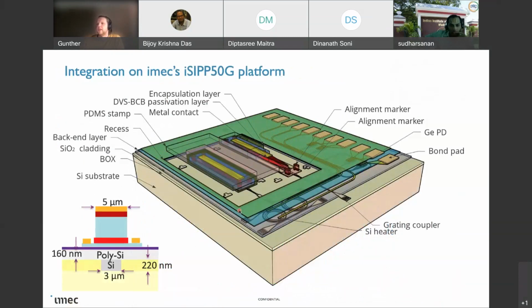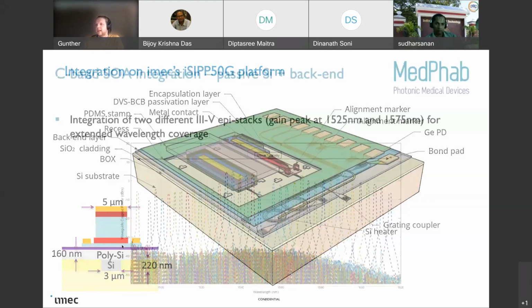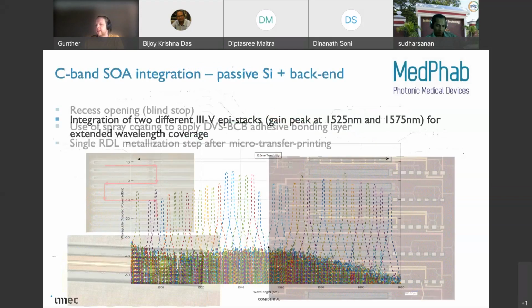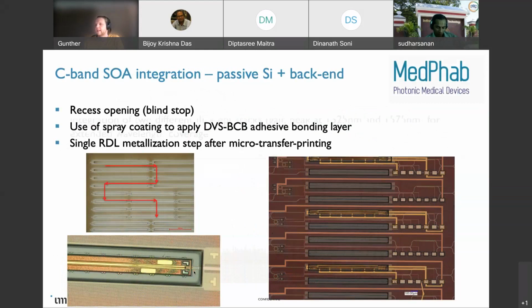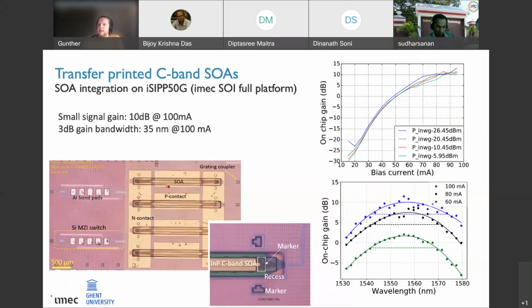Now, the next step then was to integrate on IMEC's iSIPP50G platform. I've already shown you this cross-section here. This is how the amplifier cross-section looks like. So it's similar as before. The mode is partially in the silicon and partially in the III-V. And I've also shown you here how we can transfer print inside recesses on the silicon photonics backend. So this then resulted in the first SOAs integrated on an iSIPP50G silicon photonics circuit. So that comprises high-speed modulators, high-speed detectors, switches, and the passives. So these SOAs currently have a gain of about 10 dB for close to 100 milliamp drive current.